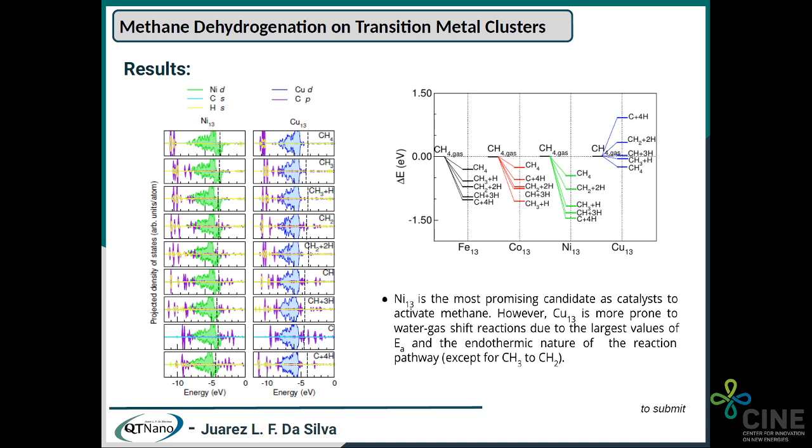Another important result is that we can take the CH4 in the gas phase as a reference. We can also propose this type of graphic, of scheme, that I can show you, where among the studied metals, nickel is the paramount to form CH3 species, but it is really near cobalt. However, when you look at copper, the CH3 species are at more positive energy values, also in agreement with all the dissociation energy tables, that nickel has a preference to form carbon depositions rather than copper.